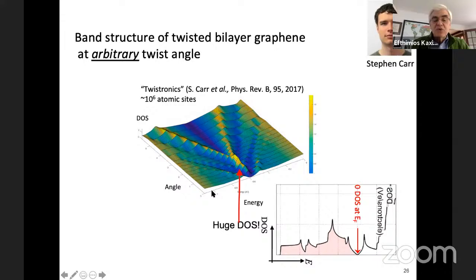And this is at zero twist. But if you increase the twist angle a little bit, about 1 degree or so, a little bit over 1 degree, you see this huge density of states at the zero value of the energy.